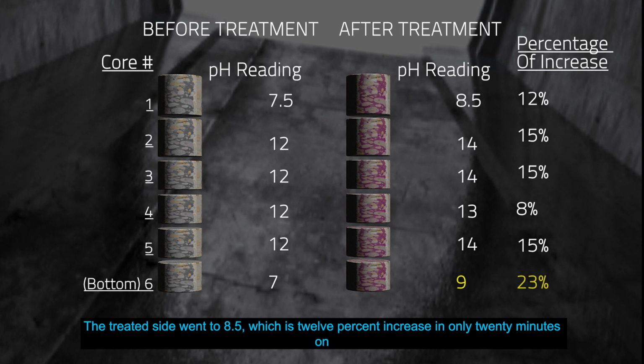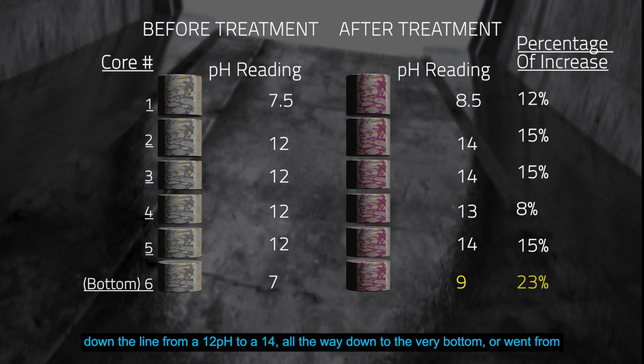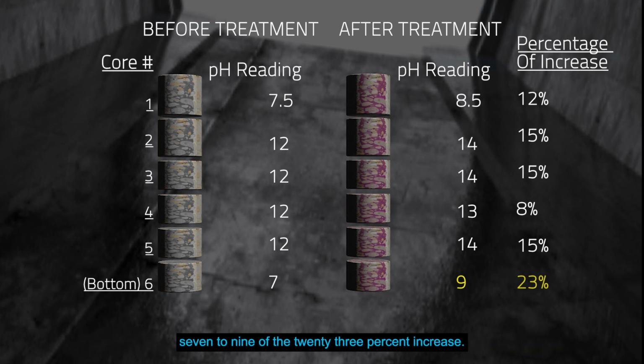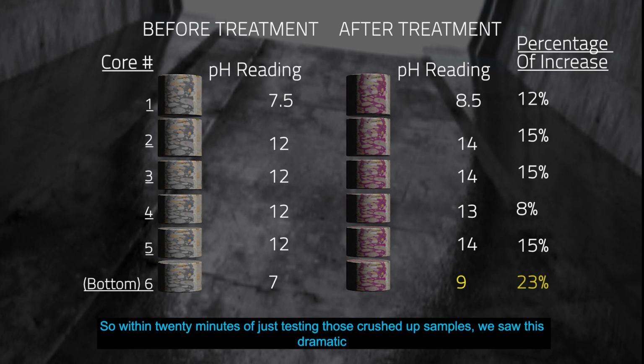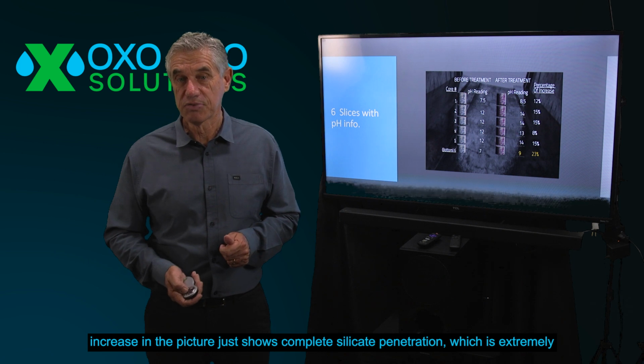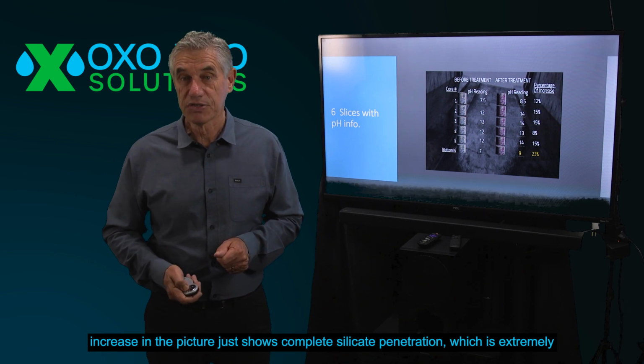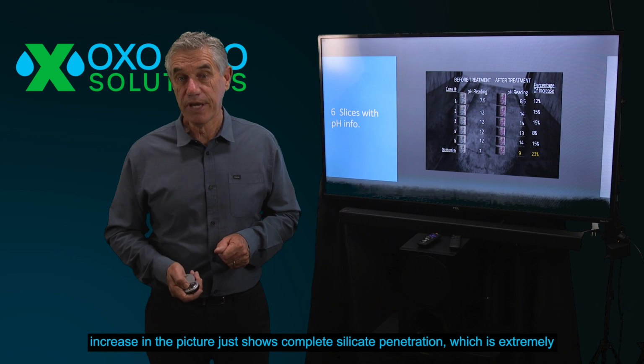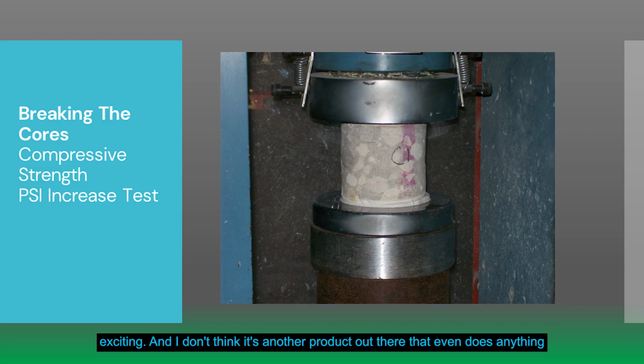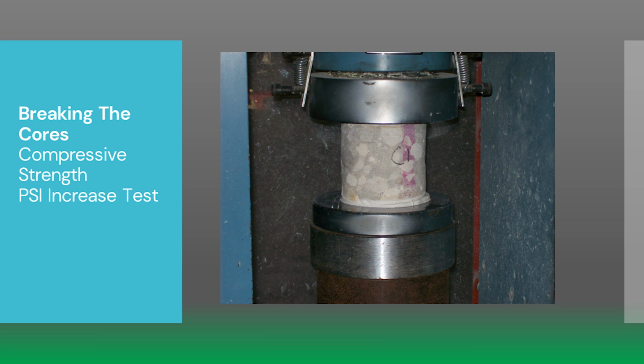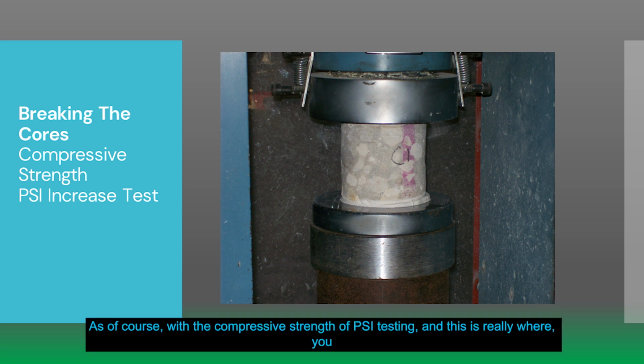The treated side went to 8.5, which is a 12% increase in only 20 minutes. On down the line, from a 12 pH to a 14, all the way down to the very bottom, where it went from 7 to 9 with a 23% increase. So within 20 minutes of just testing those crushed up samples, we saw this dramatic increase in the pH, which just shows complete silicate penetration, which is extremely exciting. And I don't think there's another product out there that even does anything similar to this at all.